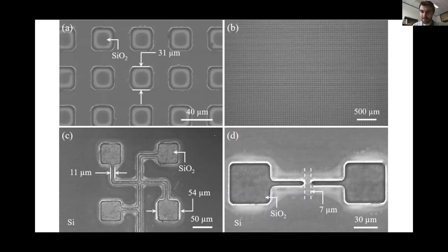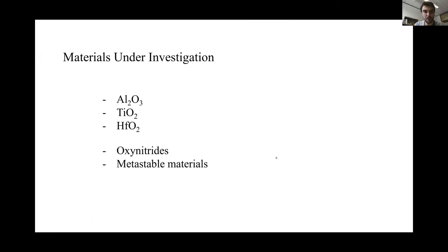And again, this is a SEM of the first sample that we had. Again, that's probably not the best quality, but the key point is the temperature and the fact that it is possible to deposit oxides at room temperature using 172 nanometer light sources. So you deliver only optical energy, only photons are your main source of energy to initiate chemical reactions. So we believe this is extremely powerful. So our plan is, we're planning a couple of experiments to do alumina, titania, hafnia deposition at room temperature, and hopefully to do multi-stacks of these materials in the future.